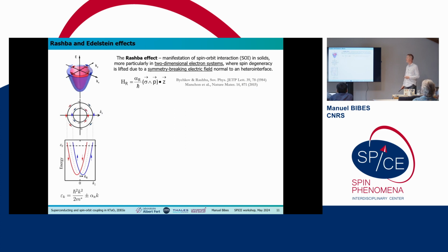So just a reminder of the Rashba effect. You're probably all very familiar with that, but that's a manifestation, of course, of spin-orbit interaction that comes into play when you have broken inversion symmetry. That's the Rashba Hamiltonian, which leads to a splitting of the bands along the k direction. Then in the simple two-band model, you have two Fermi contours, and at each point in k, the spin is locked perpendicular to k. So you have this spin-momentum locking with chiral spin textures in both contours with opposite chiralities.